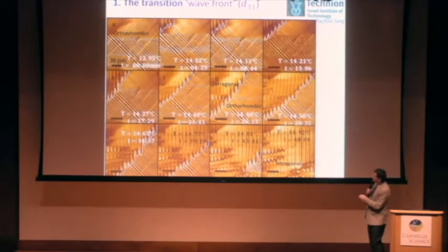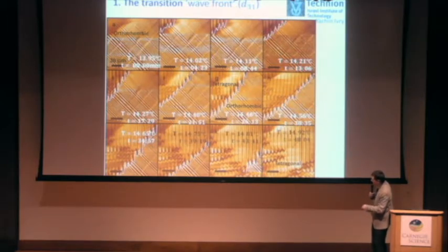And then when the shear exceeds a certain value, we can see leftovers of pinning sites. So this is what we see in here. This wavefront goes down in this direction. And after it crossed, you see that there is a gradient here, then you start getting this kind of islands, pinned islands, and the transition is complete, and you still have these areas.